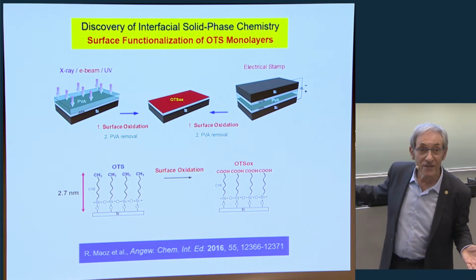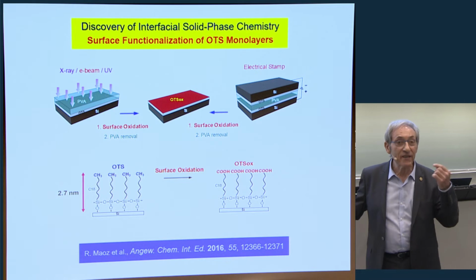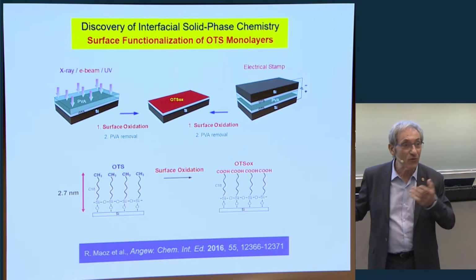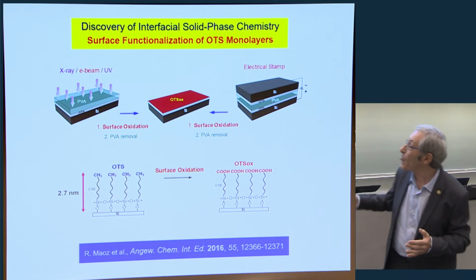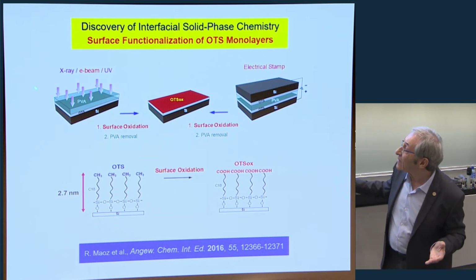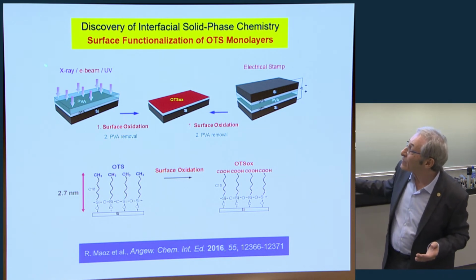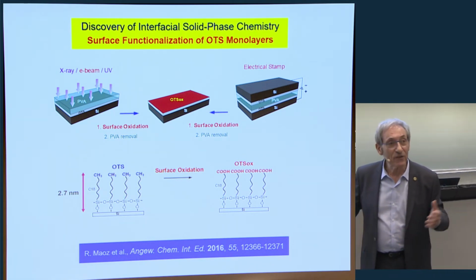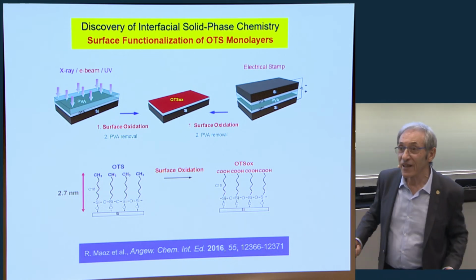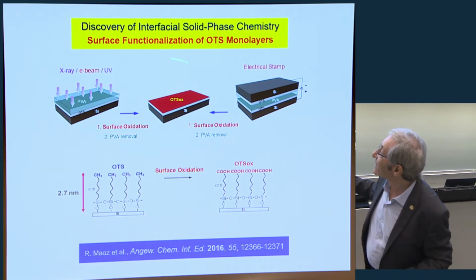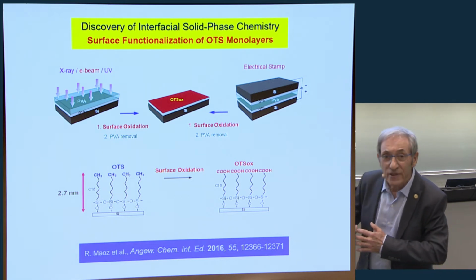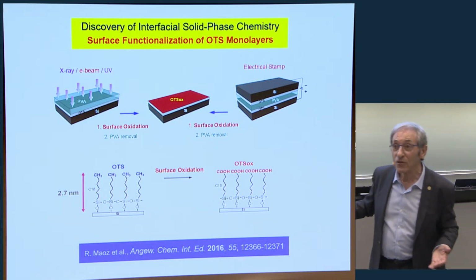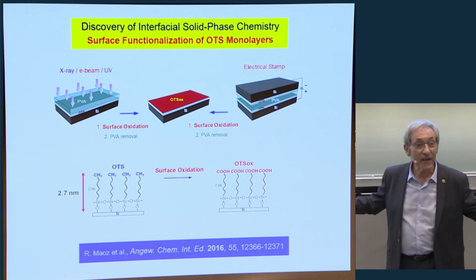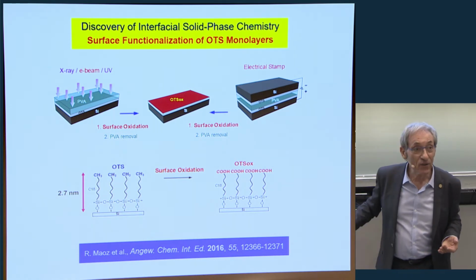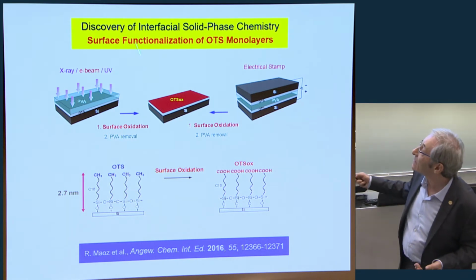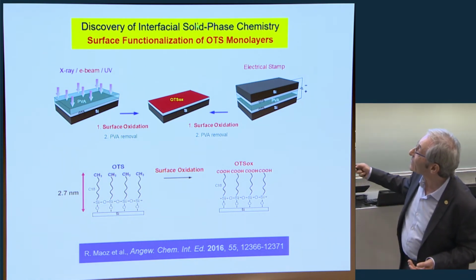The PVA is perfectly stable. So the PVA now provides the oxygen needed for this reaction instead of water. It's absolutely exactly the same. And as it turned out, probably when we say X-ray and UV, we are talking again about electrons, because X-rays extract electrons from the surface. In this case, you can use electrons with different energies. Here in the stamp, we are talking about something like 10 volts that you apply, and it works as well as high energy electrons or X-rays. And this is what we refer to as interfacial solid phase chemistry.